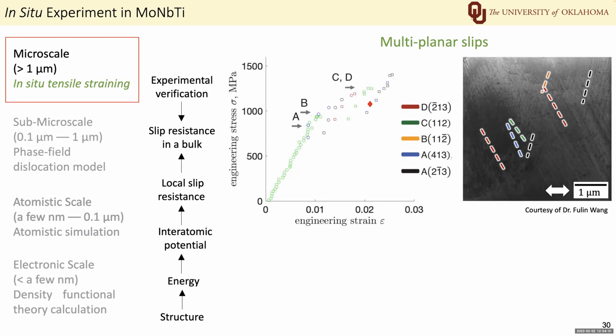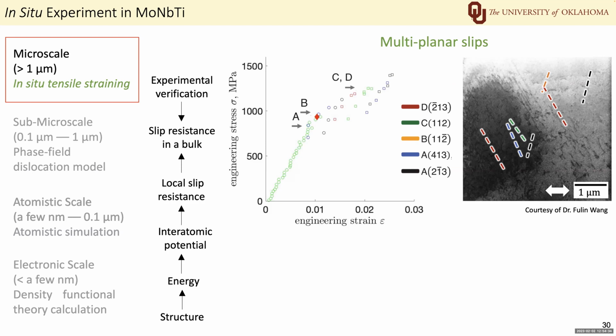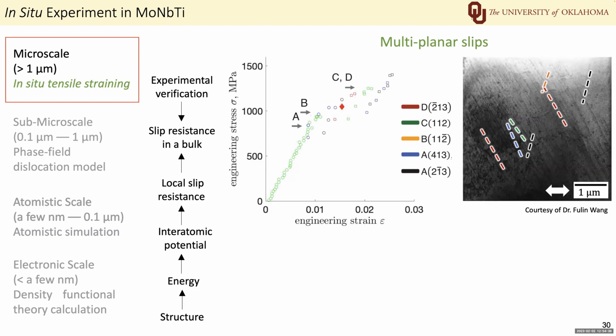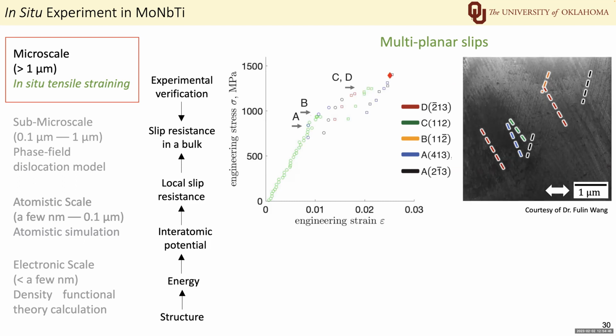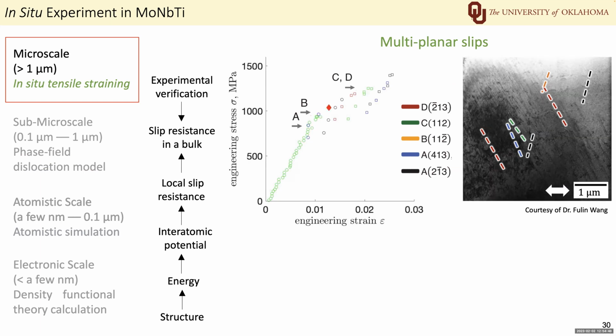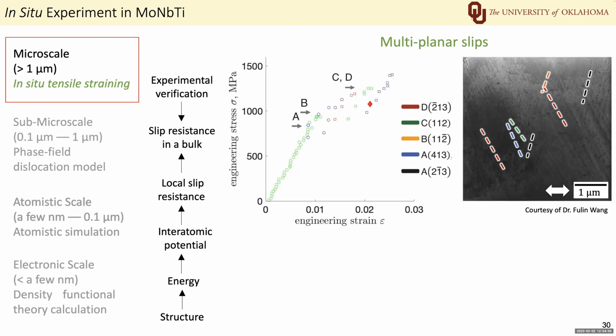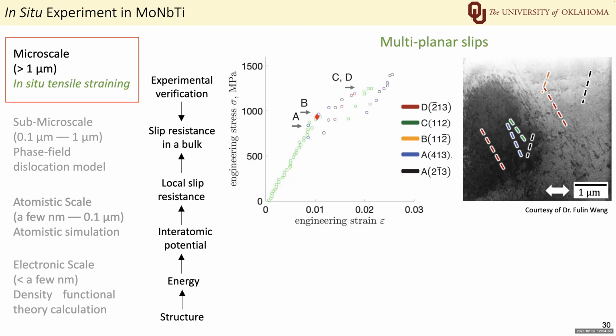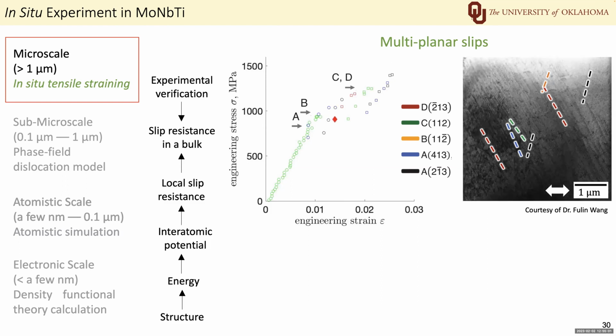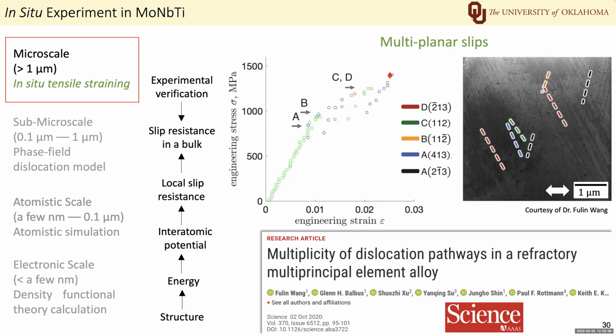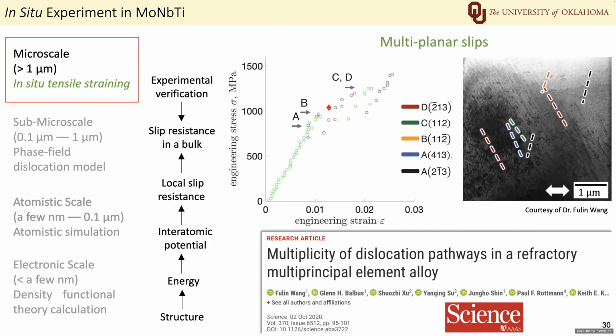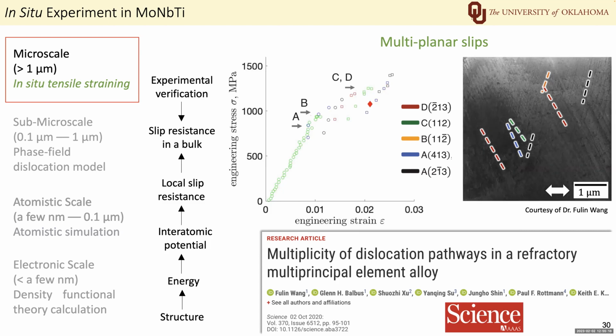They found that the dislocations tend to glide on the 112, 123, and 134 planes, but rarely on the 110 plane. This verified our simulation results and confirmed that the plastic deformation in molybdenum niobium titanium indeed occurred by multi-planar slip. So then based on both computational and experimental results, our joint paper was published in Science in 2020.